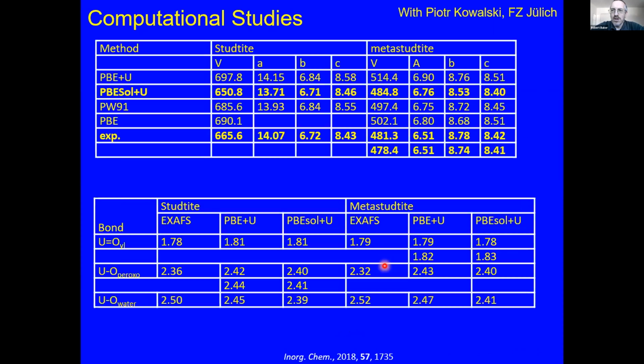That's about as far as you can go by looking at MO diagrams. So we wanted to look in more detail using some computational studies. So in collaboration with Peter Kowalski, we benchmarked our powder patterns against a number of different density functional theories, and we found that PBEsol+U gave the best fit. And just to confuse everybody, this U doesn't stand for uranium, it's the Hubbard U parameter.